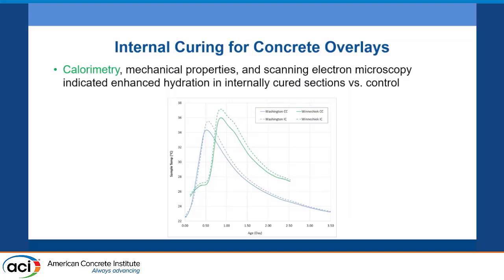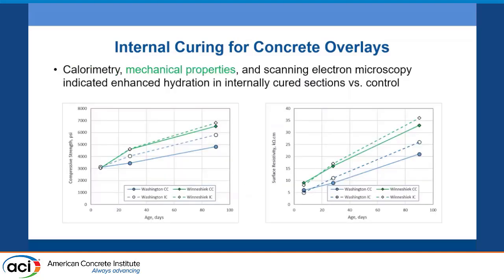So you can see calorimetry is indicating enhanced hydration through the first several days after placement for both the overlay and the conventional section. The difference between the dashed line is a little bit greater for the overlay, so potentially indicating that there was maybe a little bit of enhanced benefit there for the concrete overlay section.